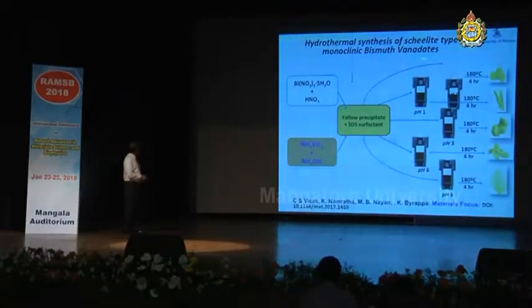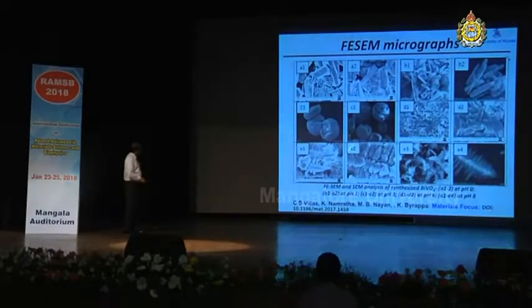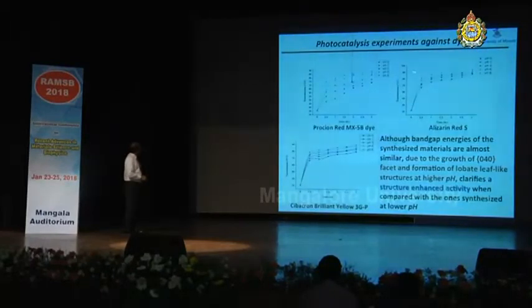And now briefly I am going to speak about the bismuth vanadate, another very attractive material, a multifunctional material showing both photocatalytic activities and also the magnetic properties. These are some of the characteristic images of the bismuth vanadate with varying pH of the medium. And we have tested several dyes for their photocatalytic activity, like alizarin red S and Procion red, and also Cibacron brilliant yellow, and we could get good results.